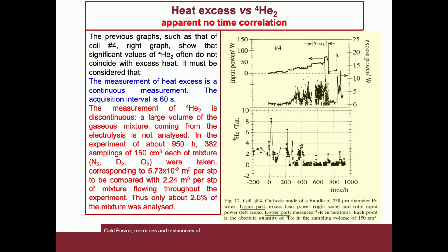In the experiment of about 950 hours, 382 samplings were carried out, each of 150 cubic centimeters of mixture consisting of nitrogen, deuterium, and oxygen, corresponding to 5.73 × 10^-2 cubic meters under normal conditions, to be compared with 2.24 cubic meters under normal conditions of a mixture flowed throughout the experiment. Thus, only about 2.6% of the mixture was analyzed.